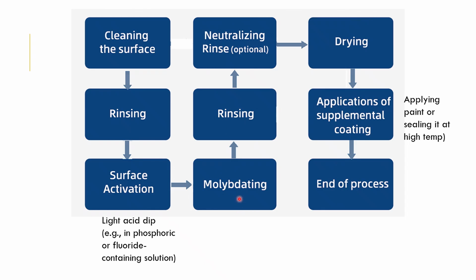After rinsing, this molybdate coating happens in a slightly basic condition, right? So if you feel that you need to neutralize it, you give a dip in a slightly acidic solution. So it is an optional process. Certain process we do it, certain process we don't do it. Then go for drying it. Once it is dried, then if required, give the supplemental coating, that is to fill up the micro cracks. So you can apply the paint or you can give a high temperature. Surface can be heated to high temperature so that it gets sealed. So with that, the process gets end. The product is ready for the application.